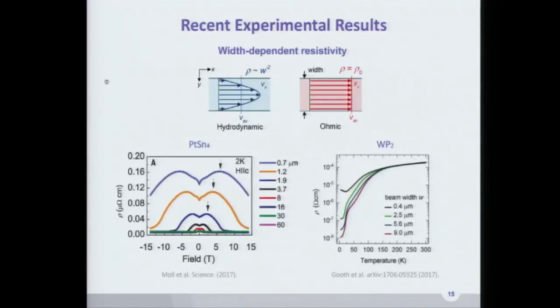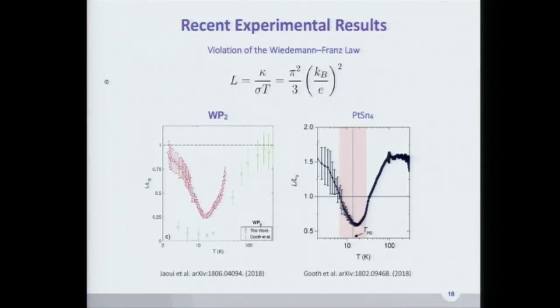Another thing that's surprising is that most of this happens at lower temperature, which was really surprising to me, because you expect that as you go to lower temperature, quantum physics becomes more and more robust. And in this case, you go to lower temperature and you see very classical physics. That's kind of weird. So we also were inspired by the fact that people had measured in tungsten phosphide, in particular, a strong violation of the Wiedemann-Franz law, something that relates how electrons and phonons are transported in a material.